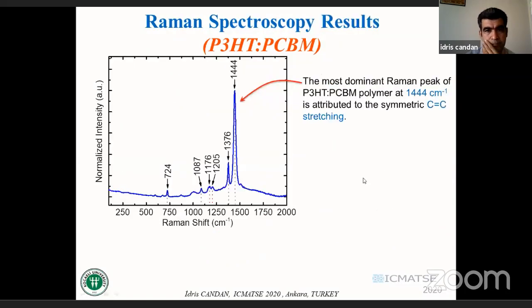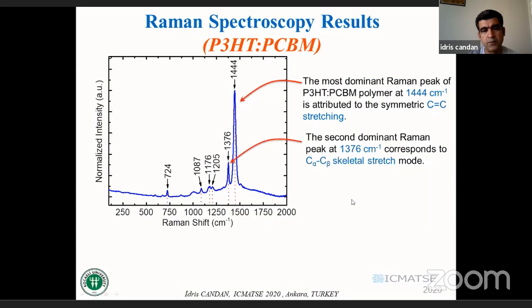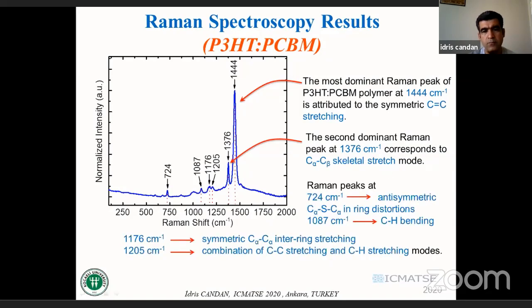And all results show that the most dominant Raman peak of P3HT:PCBM mixture at 1444 per centimeter is related to symmetric C=C stretching. And the second dominant Raman peak at 1376 corresponds to the C alpha, C beta stretching mode. And the other Raman peaks at 724, antisymmetric C alpha-S-C alpha in ring distortion,